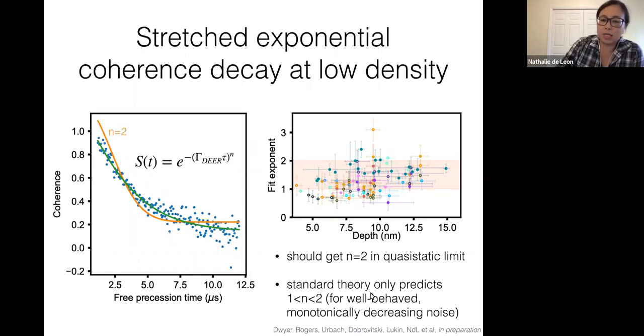In particular, the standard theory only predicts that this n should be between 1 and 2. You get an n of 1 if you have a perfectly white noise bath, and an n of 2 if you're in this quasi-static limit. But if we just did this fitting across all of our data sets in my group and in the Lukin group, you can see that we actually get quite a few that fit to an exponent that's below 1, and that you get lower and lower exponents as you approach the surface. So for shallower NVs, you get more anomalous stretched exponential decoherence.